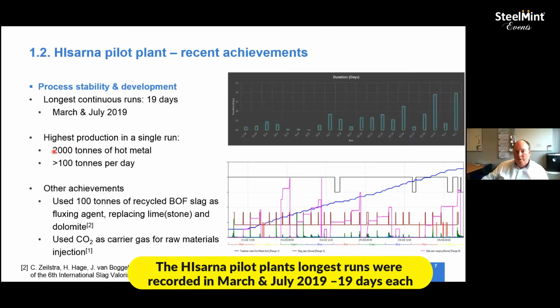The highest production in a single run was 2,000 tons of hot metal, so just over 100 tons of hot metal a day. This graph shows the blue line, which is the continuous increase in hot metal weight tapped. The pink line shows the slag taps, so we weigh everything we put in, and everything that comes out is weighed, so we know exactly where everything went, hopefully. We also weigh all the dust and stuff like that. The only thing we can't weigh is the gas production.